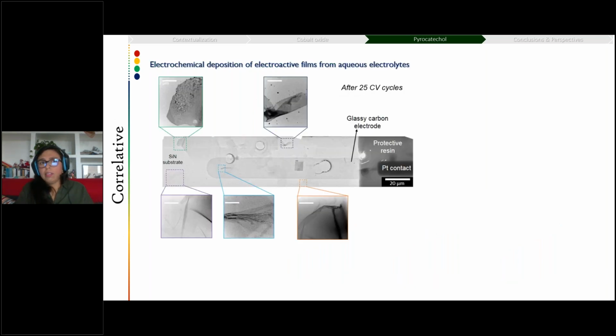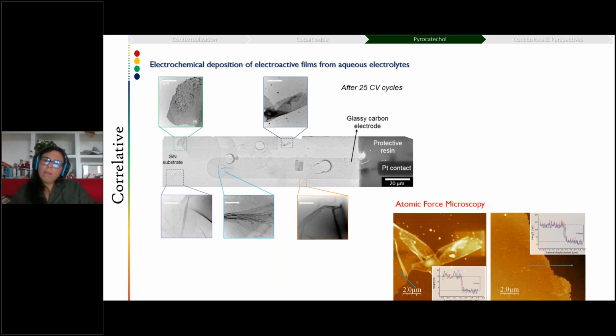Another thing that this allowed us was to observe that effectively upon several cycles, like 25 cycles, we form a film on the surface of our electrode, but more so beyond the electrode, which is probably related to the fact that the material is also electron conductive, so the reaction can take place also far from the electrode. And if we do correlative atomic force microscopy to see the thickness of the material deposit, we see that there is a layer of around 10 to 15 nanometers in the film, meaning that probably this is not a single layer material, but a stack of different materials that prefers to spread away instead of keep stacking on itself, because the uniformity of the material is quite extended.